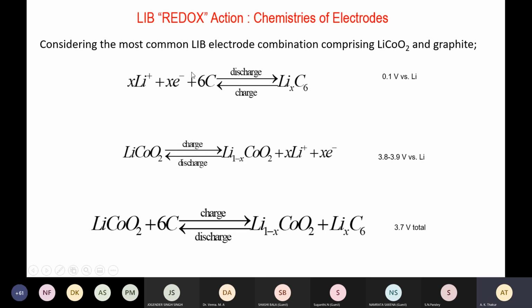The common redox mechanism is from the anode, lithium ion first. In the anode, lithium ion is to be inserted, intercalated. So 6 carbon atoms combine with x lithium to create LixC6, and this Li comes from the cathode, that is lithium cobalt oxide, which releases partial lithium, creating a structure Li1-x cobalt oxide with x not more than 0.33, beyond which this structure would become unstable.